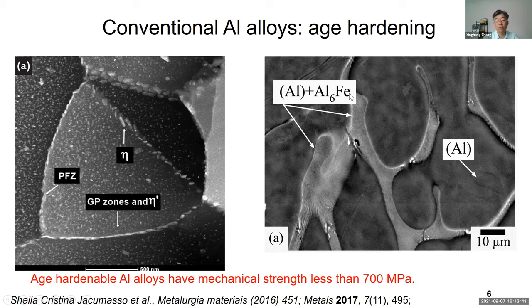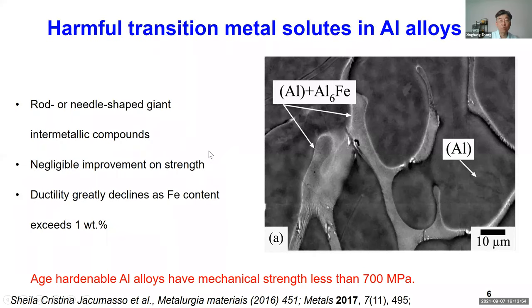And if you introduce certain solutes like iron, chances are by casting you form giant intermetallic precipitates, and that's really bad because this stuff is very brittle. This is why industry actually shied away from adding a lot of iron. In most cases you add less than 1%. If you add more, you run into trouble getting these giant intermetallic particles, which lead to embrittlement.